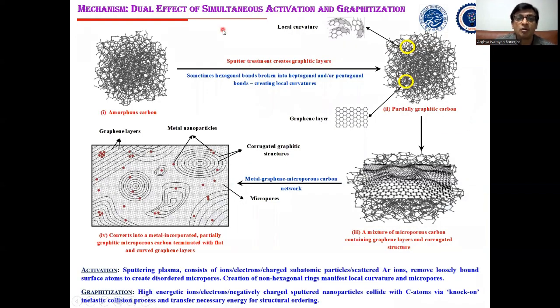Now, the mechanism of this graphitic microporous carbon network is basically a dual effect of simultaneous activation and graphitization. Initially, the amorphous carbon network, when we used under the sputtering system, due to the use of sputtering plasma and high energetic sputtered particles, some of the hexagonal bonds are broken into heptagonal or pentagonal bonds, creating some local curvature. And with further transfer of the sputtering energy, this local curvature is converted into graphene layers.